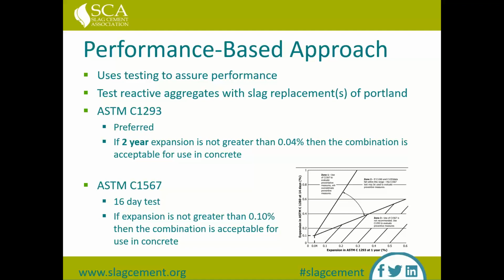So if the 1293 2-year result is not greater than 0.04%, then your slag replacement level has been shown to properly mitigate for ASR. Similarly with C1567, if your test result is not greater than 0.1%, then the SCM, the slag replacement level, has been shown to properly mitigate for ASR.